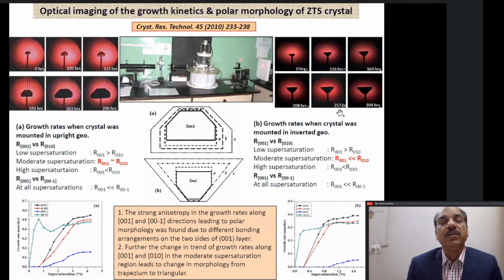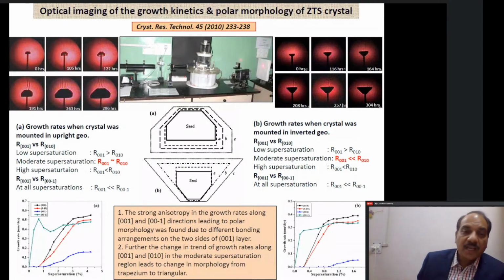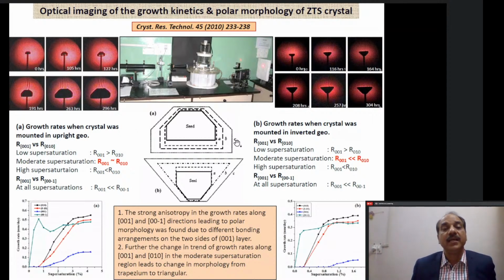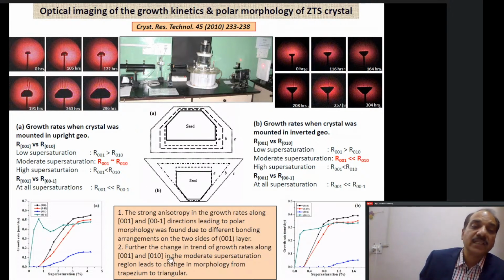And we did two different experiments. In one we mounted our crystal in the plus 001 direction, and in the other we mounted the crystal in the 00-1 direction. And we were able to tell why this crystal grows in a polar morphology, why there are more number of faces on the plus C side and fewer faces on the minus C side. The strong anisotropy in the growth rate along the 001 and 00-1 directions, leading to polar morphology, was found to be due to different bonding arrangements of the two sides of the 001 layer.